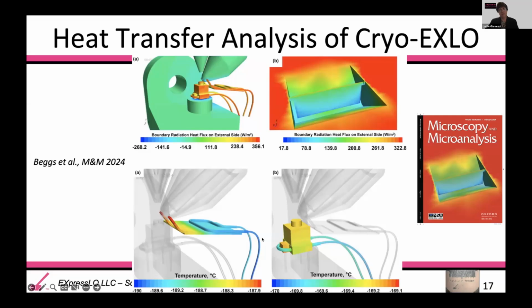This happens to be a Quorum cryo stage, which flows cold liquid nitrogen gas into this tubing. This is a cold finger here. This is the stage. You can see that the scale here from red to blue is actually minus 188 all the way down to minus 190 in this case. And so the red color is the warmest, but you can see it's still extremely within or underneath the vitreous temperatures. And this is the boundary radiation heat flux. And so you can see that this is the image that became cover art.